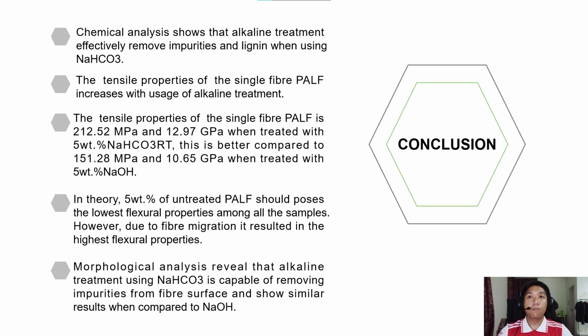So for the conclusion, we can conclude that chemical analysis shows that alkaline treatment is effective in removing impurities and lignin by using sodium bicarbonate. Next, we can see that the tensile properties of single fiber pineapple leaf fiber is able to increase with the usage of alkaline treatment. The tensile properties of pineapple leaf fiber is at its highest at 212.52 megapascal using 5% of sodium bicarbonate at room temperature compared to 151.28 megapascal using 5% of NaOH.